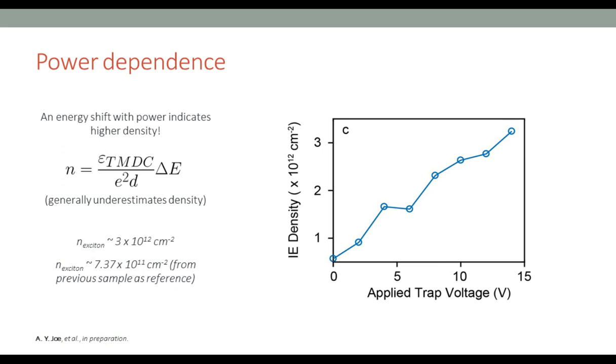And we find that without any trapping, we see a shift that's very similar to our previous sample, which is 7 times 10 to the 11 excitons per centimeter squared. But as we increase the trap voltage, we actually can increase the exciton density. And so, to put it in perspective, what do these densities really mean?